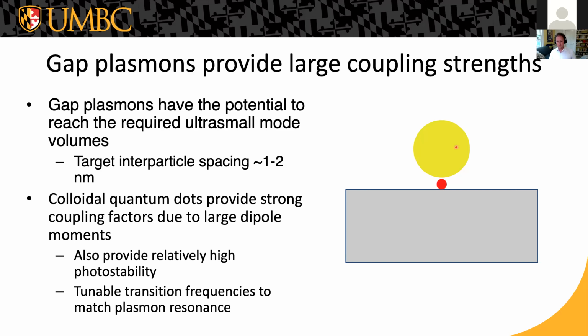And a similar configuration that's somewhat easier to realize experimentally, instead of bringing two particles together, you can bring one particle close to a metal film. And in a sort of hand-waving way, you can think of the dipole of the plasmon in the particle interacting with its image dipole inside the metal film, and again, producing a gap-plasmon resonance localized within this gap that can be down to really single nanometer type of volumes. And these are the sort of target spacings that we're looking for in our system, down about a nanometer or so. The smaller the better.